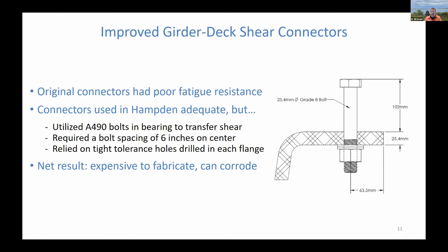It's pretty tight. It doesn't sound that tight compared to shear studs in a steel girder, but that's 2 connectors at 6 inches on center, and that's a lot of bolts, and it's a lot of really tight tolerance holes that have to be drilled in each flange because you have to get good bearing between that bolt shank and that girder flange with no slip. The net result is they're fairly expensive to fabricate. They also, since they're not galvanized, can corrode. I wouldn't say they're prone to it because they're on the bottom of the deck, but they're not highly corrosion resistant.